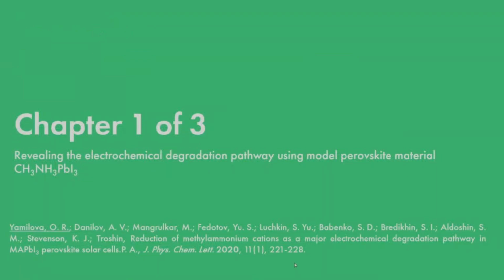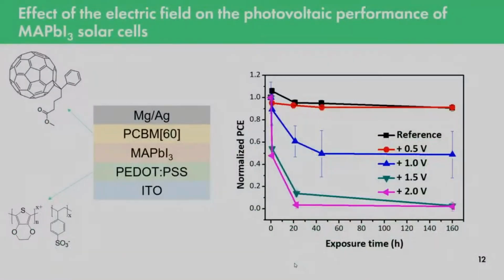So I want to start from the first part, which is revealing the electrochemical degradation pathway for the model perovskite material, methylammonium lead iodide. First of all, we wanted to confirm a suggestion that was made in the literature, that there is a threshold voltage. What does threshold voltage mean? It means that a solar cell can sustain some small voltages applied for a long time, but when we increase the voltage, there is some threshold voltage. After application of this voltage, the solar cell starts to degrade. We decided to first of all check this assumption from the literature.